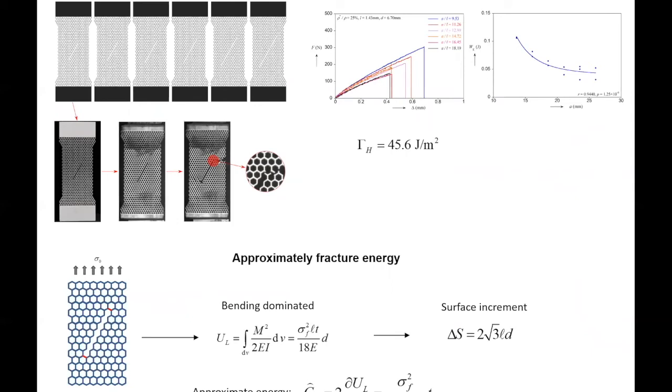And the first complication is that our crack did not go all the way up along the same line. Now, if it didn't even start that way, we would have a big problem. However, every time we zoomed in, we saw that the first couple of struts were along the same orientation as we thought it would go. So the results are still good, but then it turns. Now, whether it turns because those are the limitations of what we could print in the test.